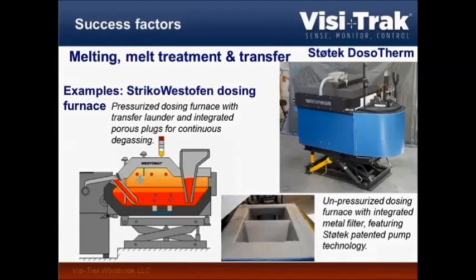Now when we talk about dosing, typically in die casting we use ladles. For high integrity die casting, there are ways to get there with ladles, but I would recommend using a dosing furnace. It helps in 2 ways. One is it really helps getting a low turbulent flow of the metal into the shot sleeve, and B, my melt quality is definitely going to be better because I can continuously degas. I can very often still filter inside the holding furnace or on the bottom of the pump. Plus I actually have an enclosed system, so I don't lose heat, and therefore I can keep the melt temperature a little lower. Plus I actually have an inert atmosphere on top, so I will get less oxidation on the metal surface as well.